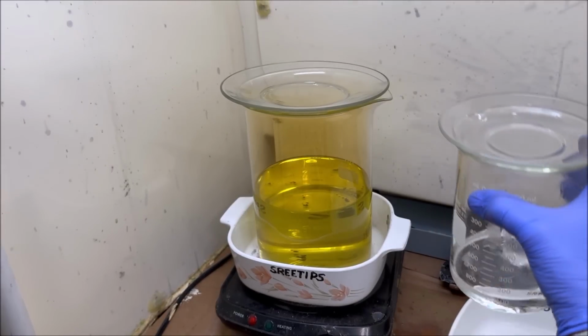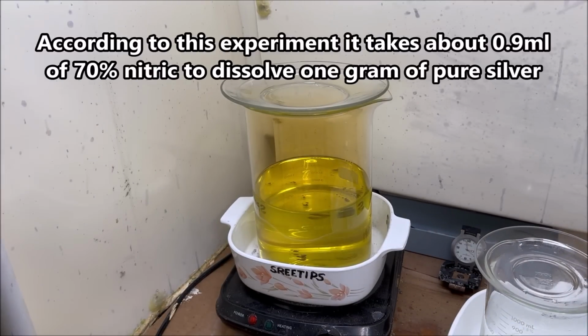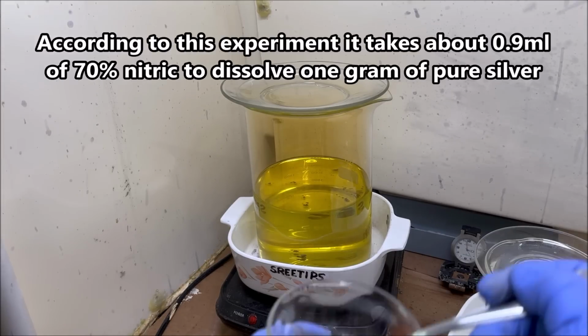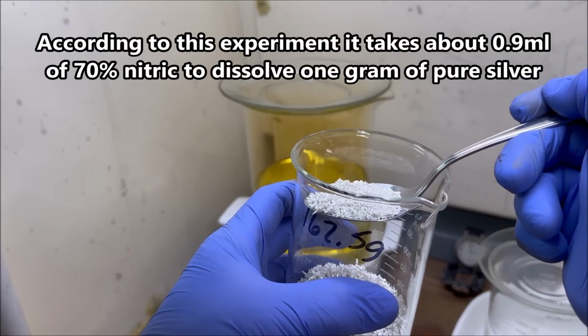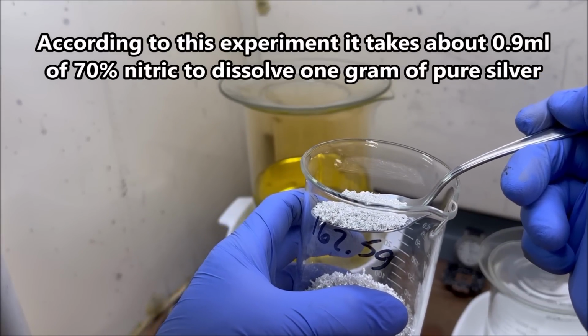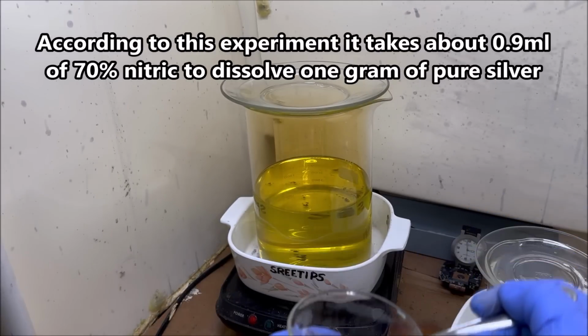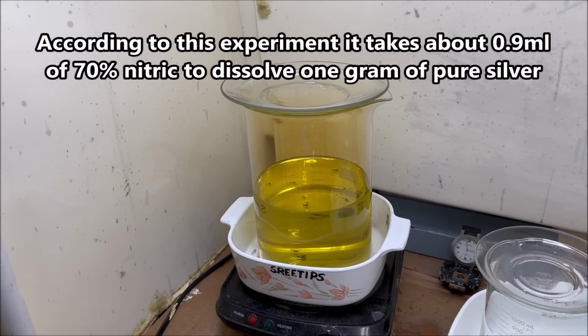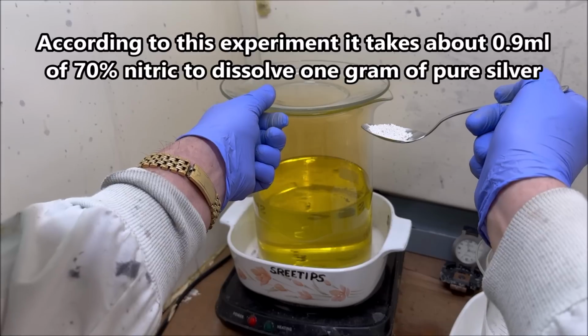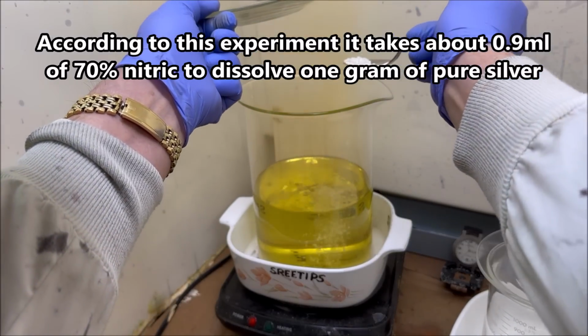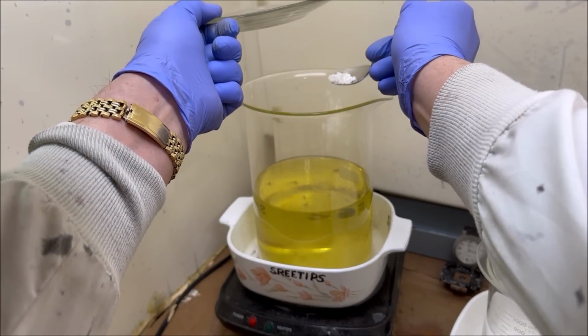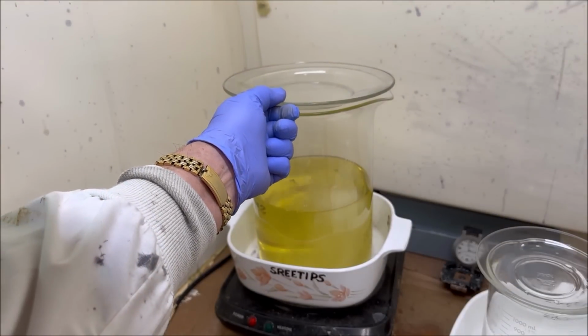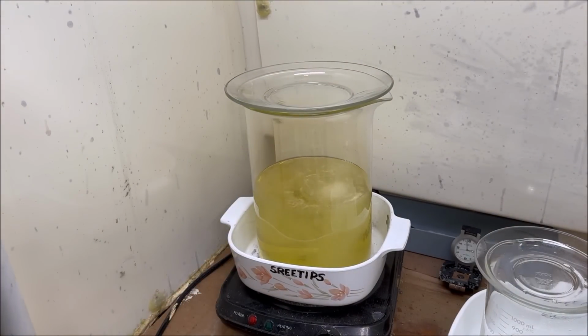Earlier in the video I said it took about 1.2 milliliters of nitric acid to dissolve 1 gram of silver, and that figure was for sterling silver. I'm not working with sterling silver here, I'm working with pure silver. So 1.2 milliliters is way too much nitric. Here I've got excess nitric in the electrolyte after all the bars are gone. So in order to remedy that, I'm adding some pure silver crystal from my silver cell to consume the excess nitric.